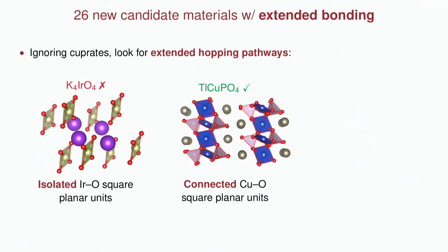So now we're down to 187 compounds, and that's a small enough number that I could actually go through and start to look at what some of these things are and further screen this down to find the best candidates. So the first thing I do is I get rid of any cuprates because those have been well studied. That's nothing new. And secondly, I consider the actual crystal structure here. In a material that has an electronic structure like the cuprates, we want some electronic conduction pathway. Basically, we still need some finite hopping. We want U to be large compared to T, but we still need some conduction pathway. Therefore, we're going to ignore any candidate in which we don't have any connectivity between these transition metals.